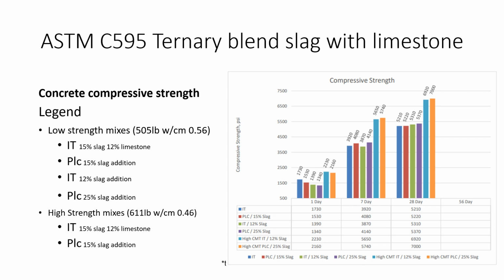Well, we look at ternary blends, right? So this is that local ternary blend that is locally here. Right, this is a test result showing it with just it on its own at 15%, and then adding in 12% slag to make it as if it was 15% or 25% in the field. So this was deliberately done at 15%, and the reason why is to help lower our global warming potential aspects. Right, when we make slag cement, we actually have to use a dryer to dry out the granules